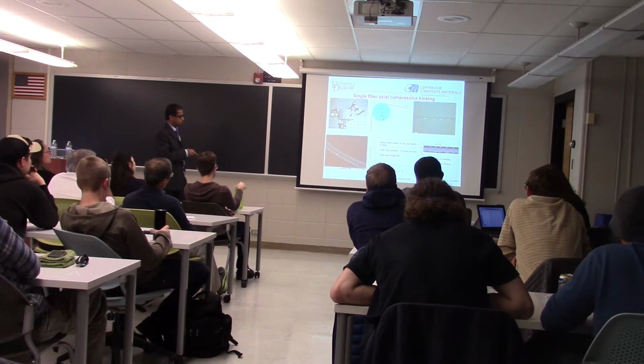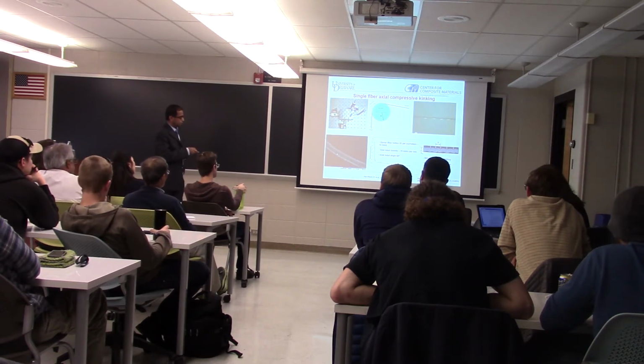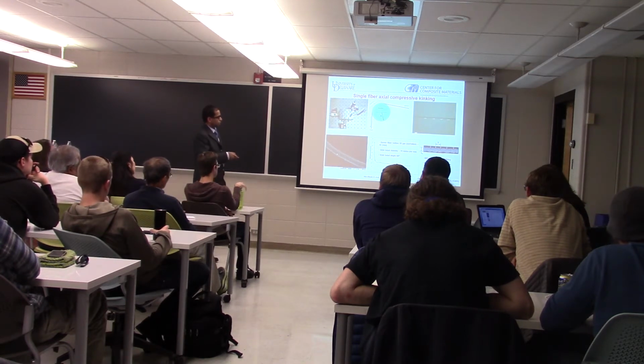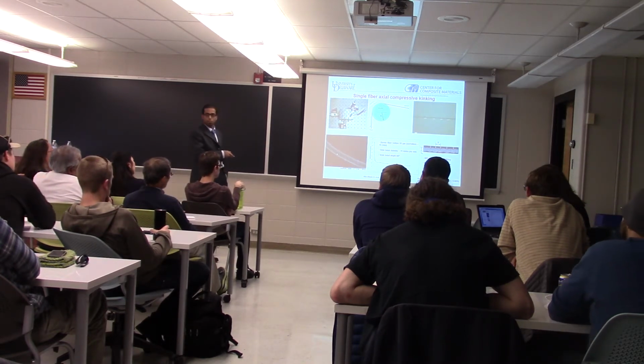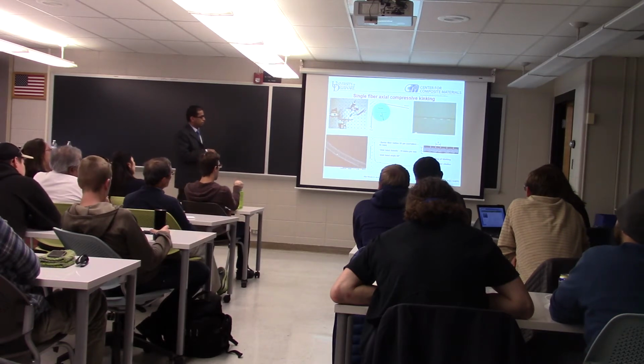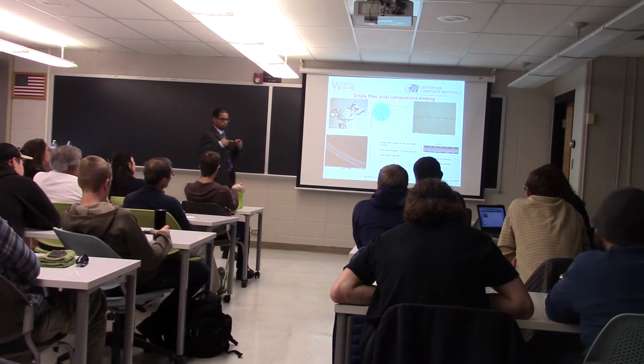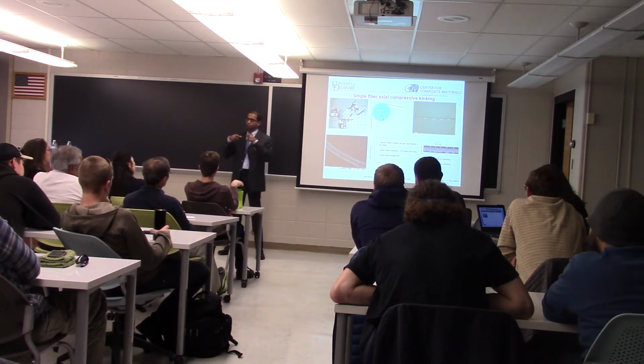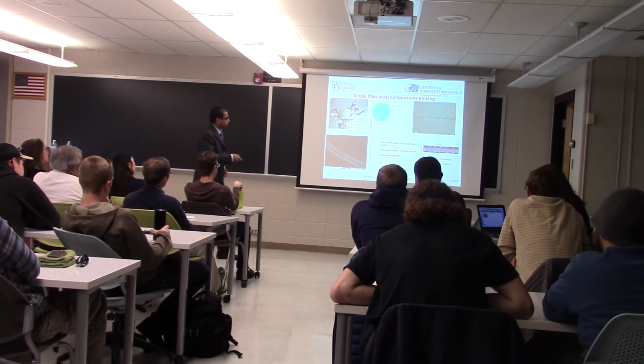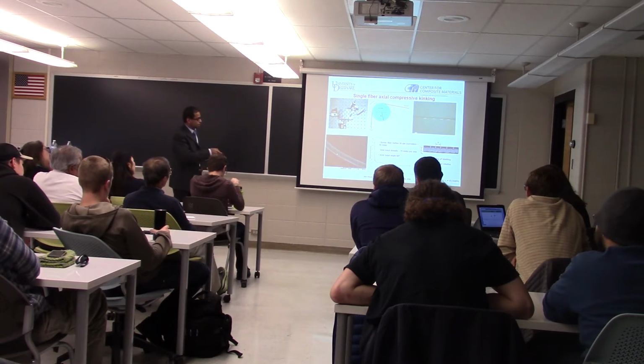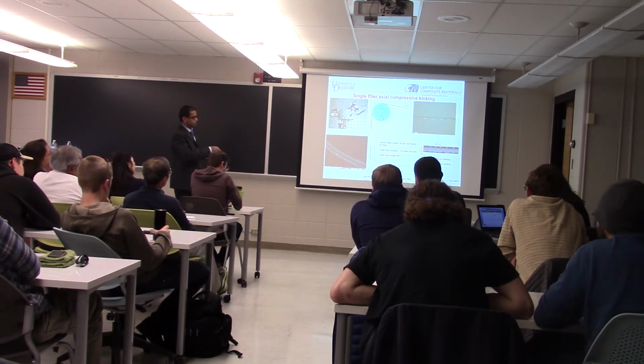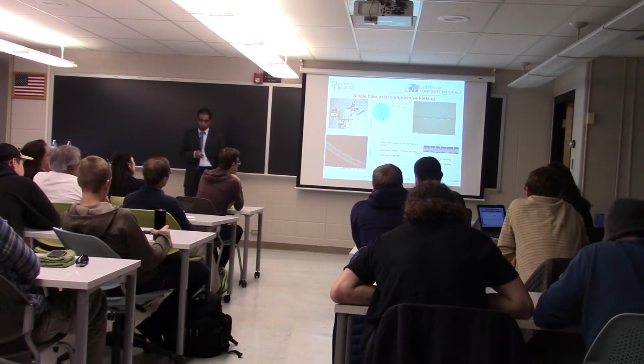And what we see here is, with the decrease in the wrapping radius, the kink band density quickly increases. And interestingly, we collaborated with a colleague who does molecular dynamics simulations. And his MD simulations of this kinking process indicate that kinking is due to buckling of these fiber chains. And also interestingly, the normalized characteristic kink density correlates well with the experiments.